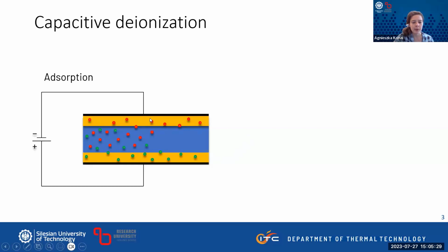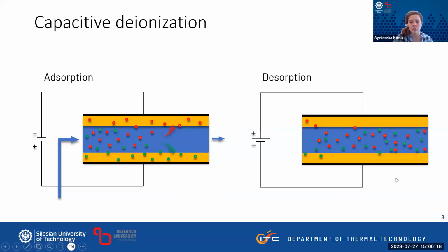And so when you apply the potential and you charge these two electrodes, when you insert a water flow between those electrodes, then the cations and anions will be electrosorbed on the surface of the charged porous electrodes. And so at the outlet of the reactor, you can get clean water. With this process, with the solid electrodes, after some time, your electrodes will get saturated with the ions. So inevitably, after the adsorption or the charging step, you need to disconnect or reverse the potential and do the desorption step, where the ions get back into the water stream. So during this discharge step, you are collecting the concentrated brine as a waste from the desalination process.